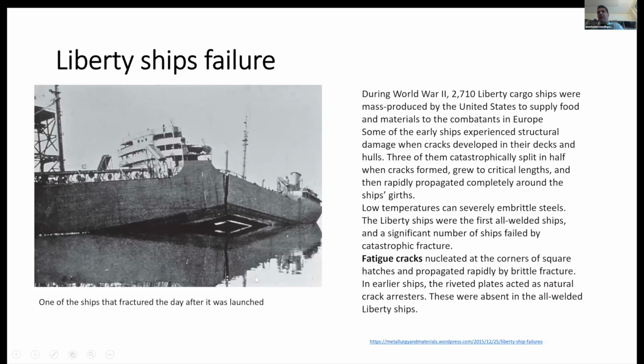We've seen also similar failures during World War II with the Liberty ships. A lot of them were very rapidly produced by the United States to supply food and materials, but they had a problem because they were all welded, and there were cracks that started from the corners of the rectangular hatches they had, and these cracks, during the floating in very cold waters, were propagating as fatigue crack failures, and led a lot of these ships to the bottom of the sea instead of the Allies.